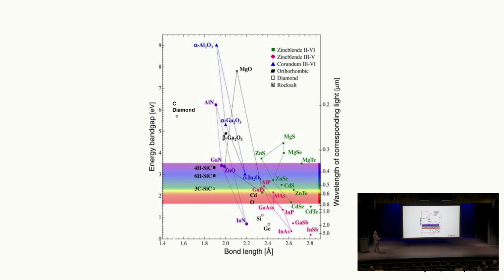This is the electronic band gap of different materials as a function of bond length. And here's the wavelength of light and the different colors that you get in the spectrum of light. What you see here is silicon. Silicon has a band gap of about 1.2 electron volts, and it's the most user-friendly semiconductor material that's widely used. Diamond is an ultra-wide band gap material, and it has a band gap of 5.6 electron volts.